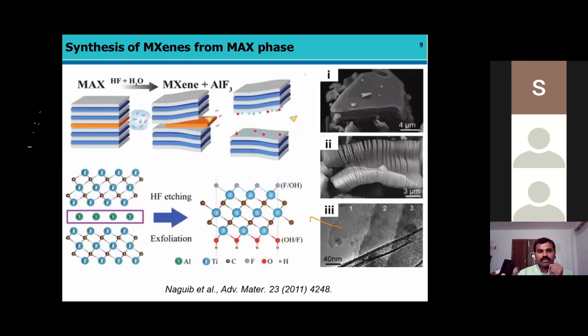Then this is the schematic representation of the MXene phase derived from the MAX phase. It was selectively removed, and you can see it in the bottom image. The HF selectively etched, and introduced new functional groups like fluoride and hydroxide on the surface of MXene, which is highly useful and induces the hydrophilic nature. You can see here some images of MAX and MXene, and it was confirmed by TEM image also.